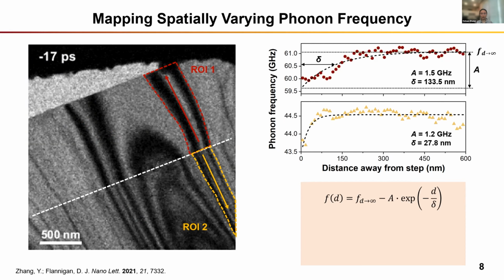As we discussed earlier, the frequency depends on the z-axis velocity and the specimen thickness. The velocity is proportional to the square root of the z-axis elastic constant, C33. And within each ROI, the thickness is a constant. So the frequency variation is directly indicative of the variation in the effective elastic constant. So the amount of reduction of the phonon frequency is equivalent to 2.6 gigapascal or 5% of reduction. So what could have caused this change at the step edge?